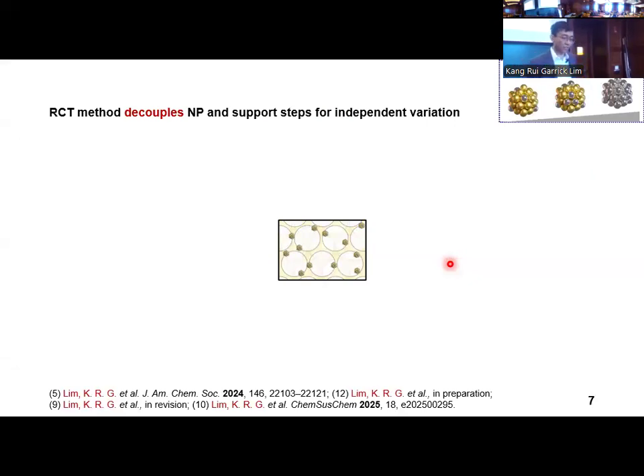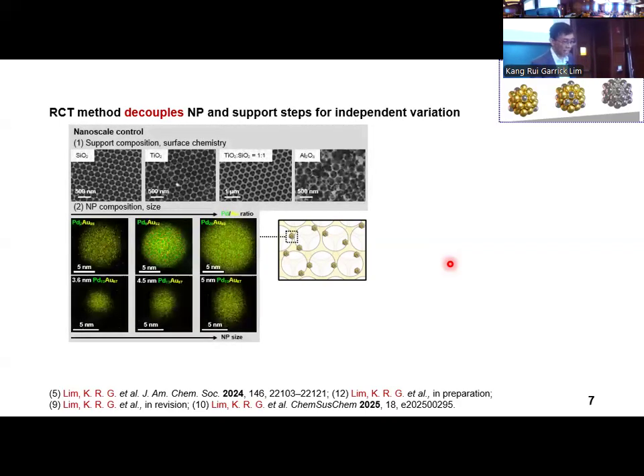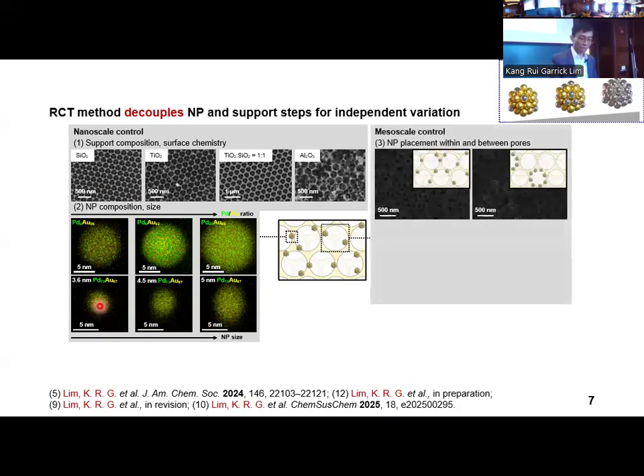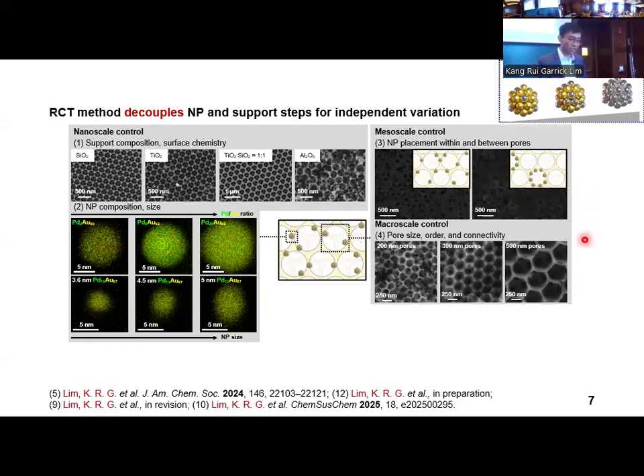The modular RCT method distinctly decouples the nanoparticle and the support formation steps for independent variation at different length scales. At the nanoscale, we can isolate and tune the properties of the support and that of the individual nanoparticles, such as the support chemistry, nanoparticle composition, and the nanoparticle size. At the mesoscale, we can control the spatial position and localization of nanoparticles within each pore, which I will elaborate from the next slide onwards. At the larger macroscopic scale, the template size dictates the RCT catalyst pore size and its connectivity to control mass transport properties.